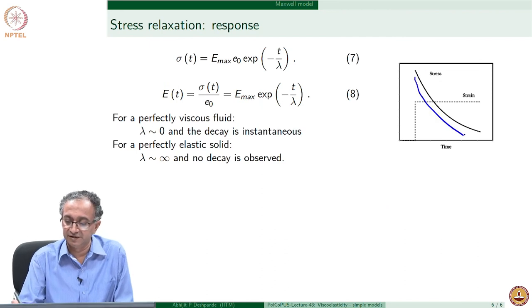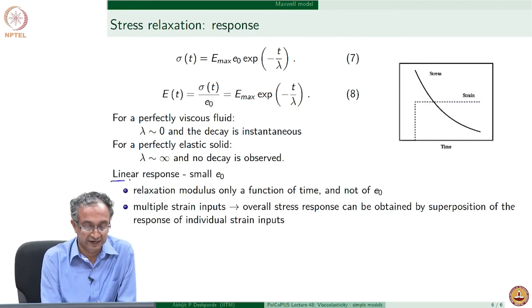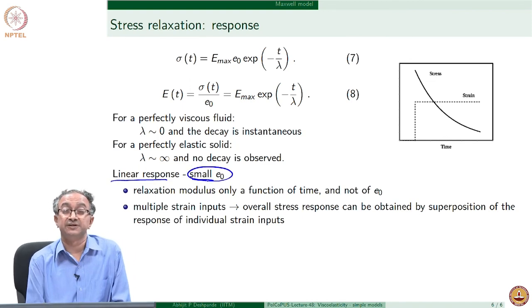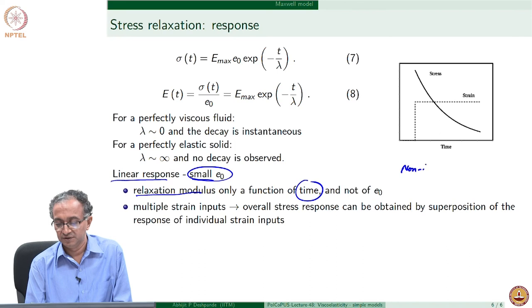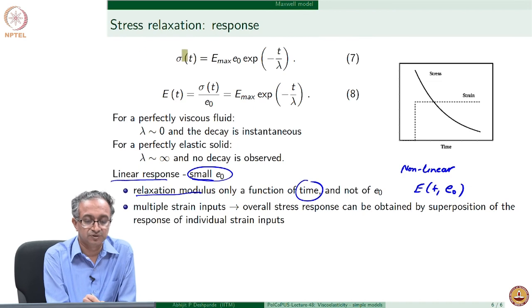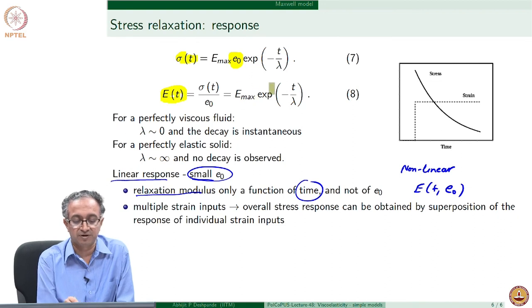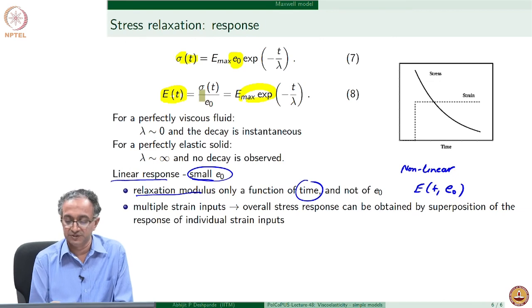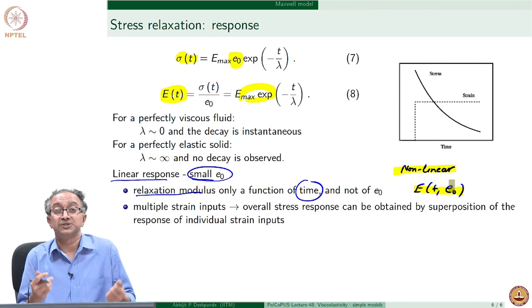The stress decay with an exponential function for a constant strain is the response the Maxwell model gives. This is valid because we are looking at only small-strain response, and the relaxation modulus is only a function of time. For a nonlinear response, E would be a function of both time and the initial strain ε₀, because the material structure has changed due to the application of very large strain. In linear response, the response variable carries no strain dependence.